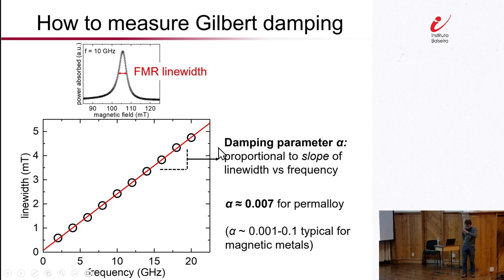Right, okay. So in this case, some people actually do carry out the experiments that way, fixing the magnetic field and sweeping the frequency. And yes, of course you would see a non-zero finite line width. The relationship though, if you were to plot line width as a function of magnetic field from such experiments, the mathematical relationship through which you can get the damping parameter is a little bit more complicated. It's not a linear relationship anymore, but you can do it that way also. Does that sort of answer your question? Okay, thank you.